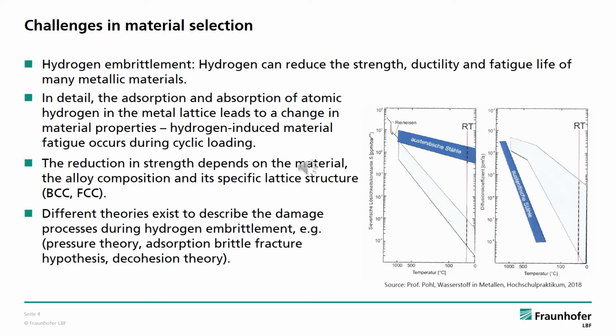In combination with metallic materials, hydrogen can reduce the strength, ductility, and the fatigue strength. In detail, the adsorption and absorption of atomic hydrogen in the metal lattice leads to a change in material properties. Cyclic loading of the materials in the medium hydrogen leads to hydrogen-induced material fatigue. Due to the different metal lattice, materials have different hydrogen solubilities and diffusion coefficients, which influence the susceptibility to hydrogen.